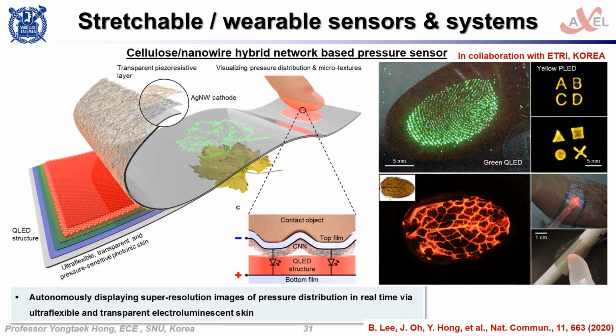Since the electrical contact varies the resistance value in the locally pressed area, we were able to make a 1000 ppi resolution pressure sensing imager, which enabled us to produce a fingerprint image and a three-dimensional structure image. For now, in order to read out the pressure mapping signal, we need an optical device like a CCD, but we can also directly reroute the electrical mapping signals by using a highly integrated silicon chip.